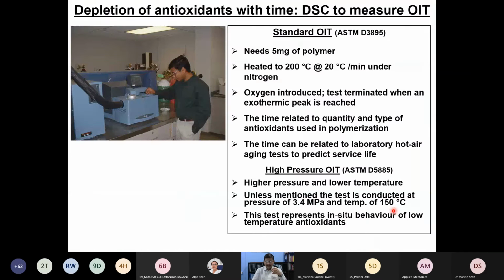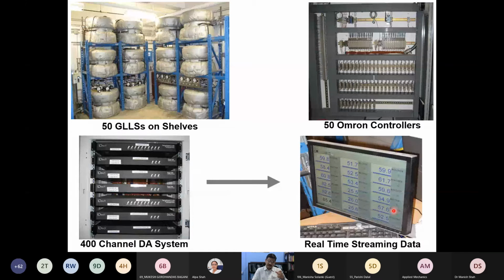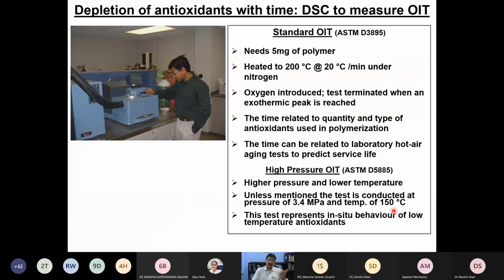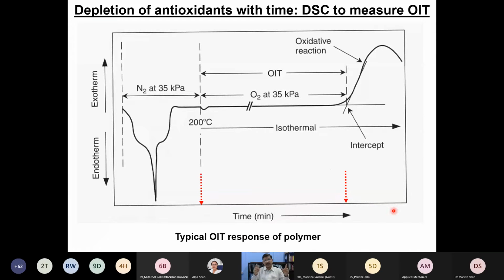As a result, not only that, after taking out the geomembrane, we also measure the OIT by using a DSC. It's a very, very simple test. It's not something very great. If you look at the OIT test, what we do is we increase the temperature of a geomembrane at a constant rate till we reach 200 degrees. Up to that point, we maintain the nitrogen environment. Once we see the constant temperature, we introduce the oxygen.